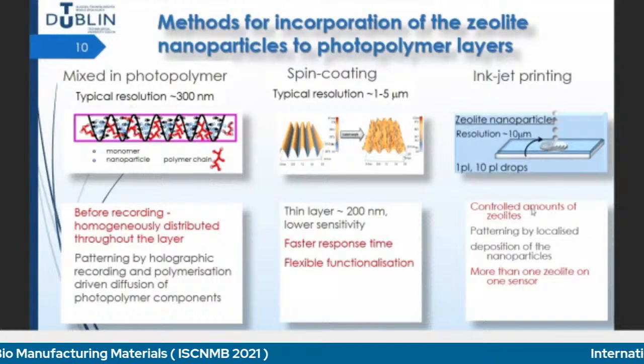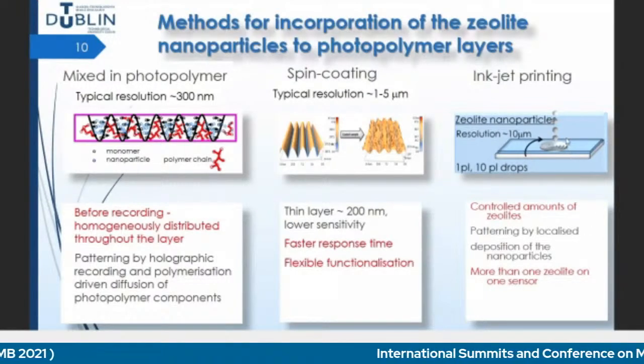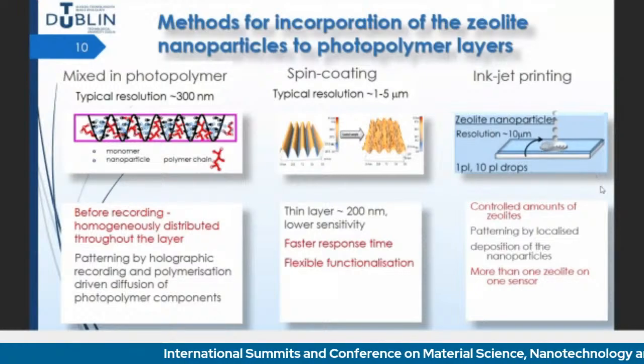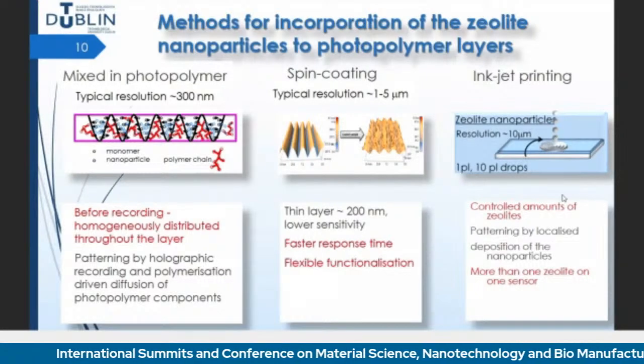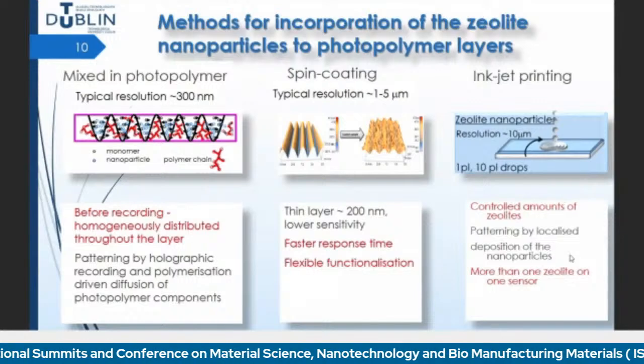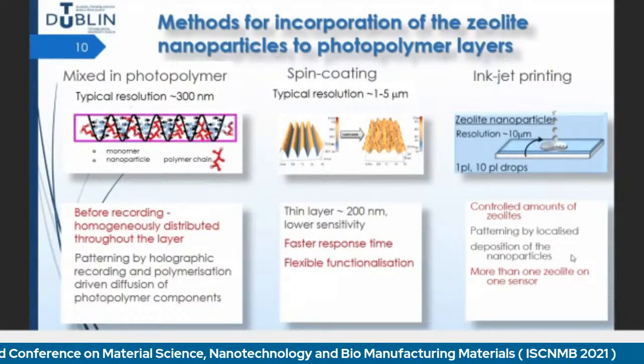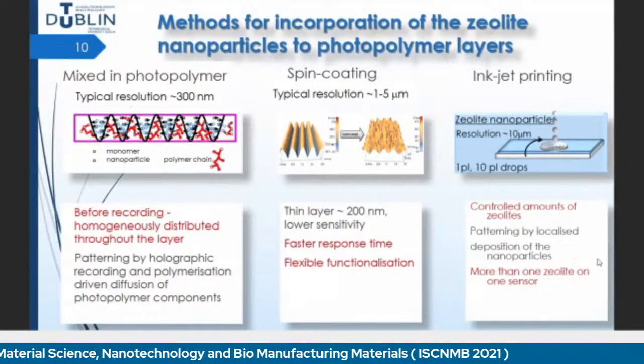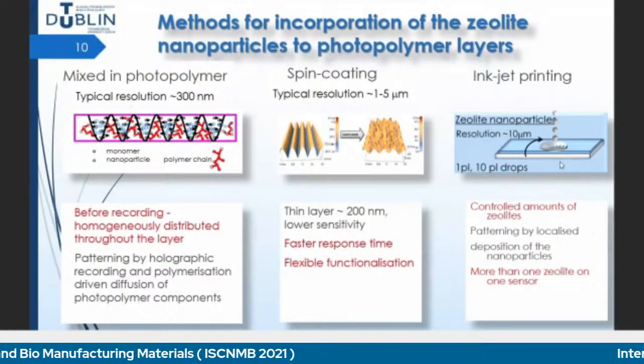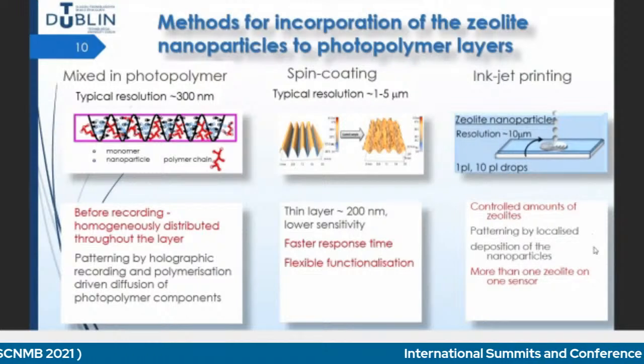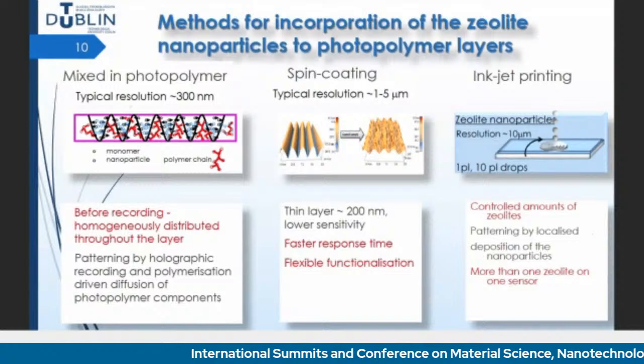material. And finally, we have used inkjet printing, where the nanoparticles are deposited in very specific areas of the material. We can control the amount, we can control the location of the nanoparticles, and we can print different zeolite nanoparticles on the same layer and have a sensor with multiple active sites for different analytes.